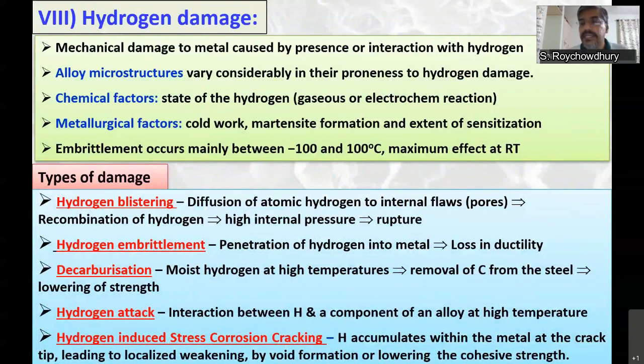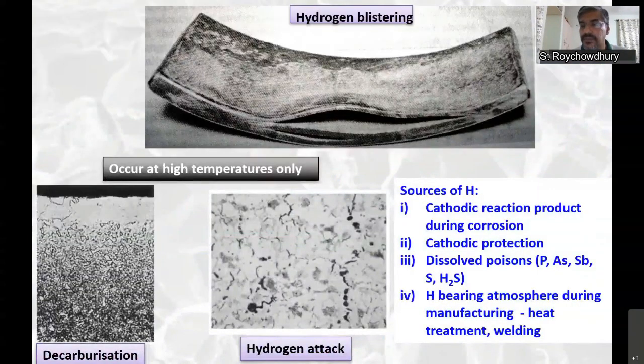Hydrogen damage, as the name suggests, hydrogen enters into the metal. Hydrogen is present in the metal in the atomic form H, and that will cause damage to the metal. What are the sources of hydrogen? Cathodic reaction is one source, where the hydrogen can be picked up by the metal. Cathodic protection also: during cathodic protection, hydrogen is liberated, so hydrogen can enter into the metal. In the water environment, if you have ions of phosphorus, arsenic, antimony, these also promote hydrogen pickup by the steel. Another source of hydrogen is during welding.